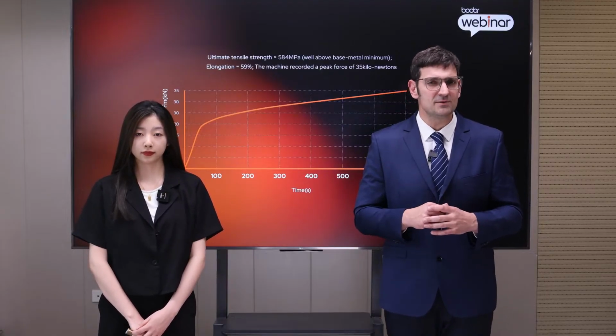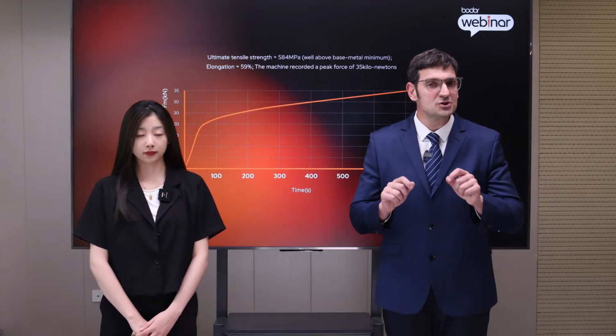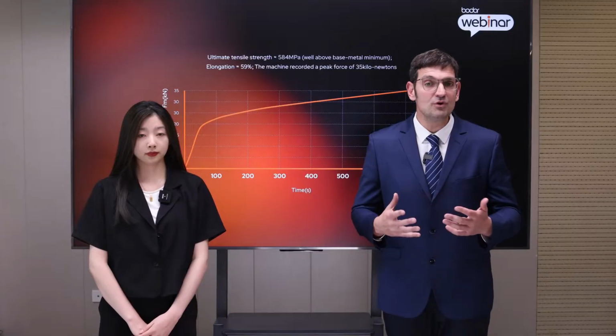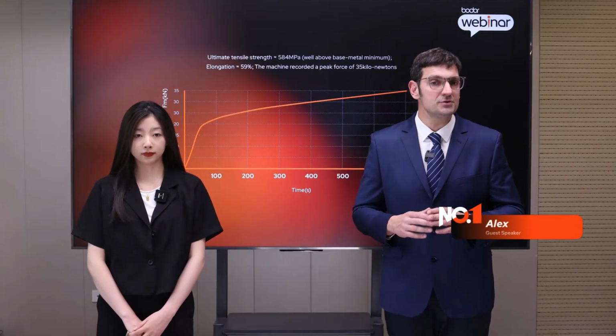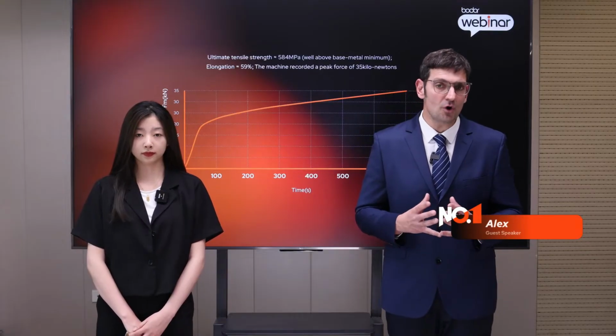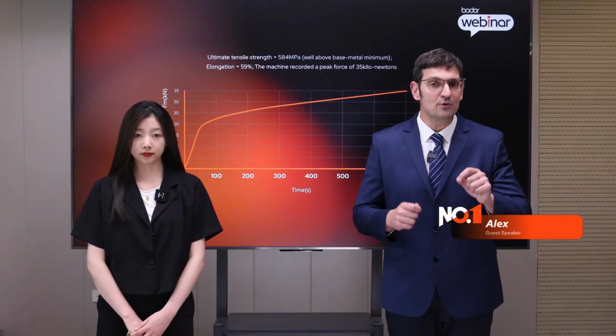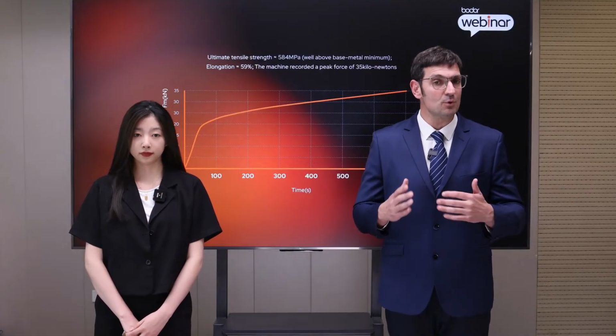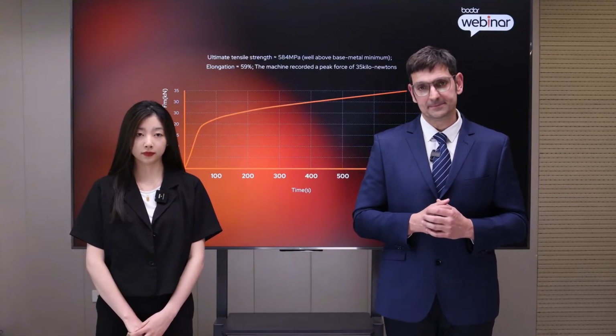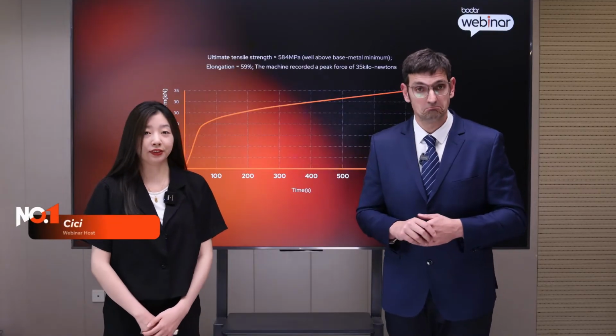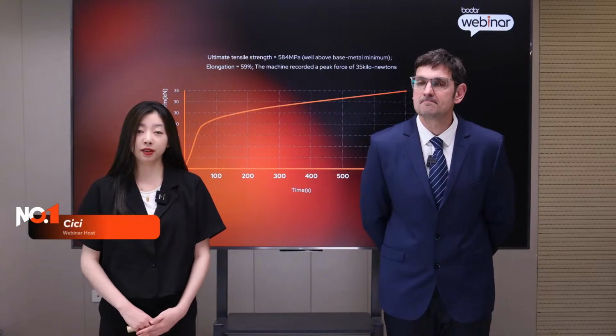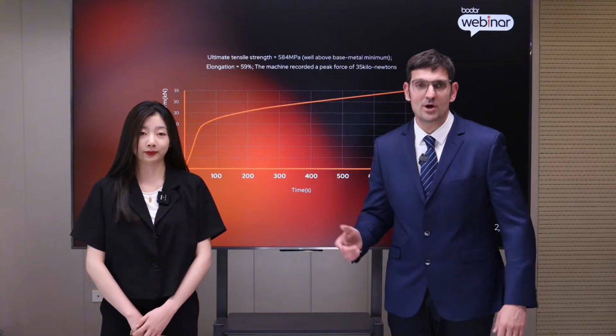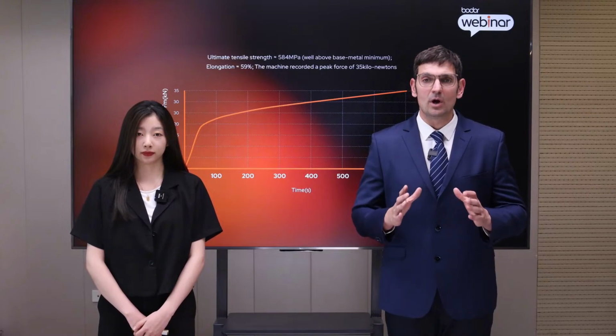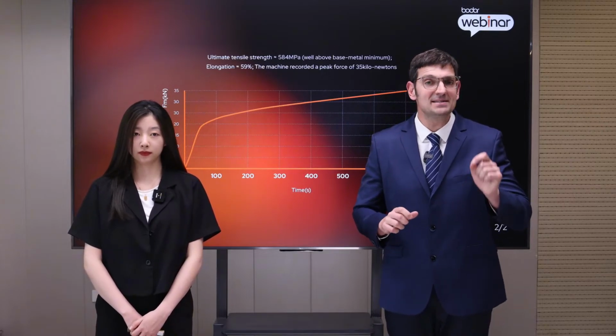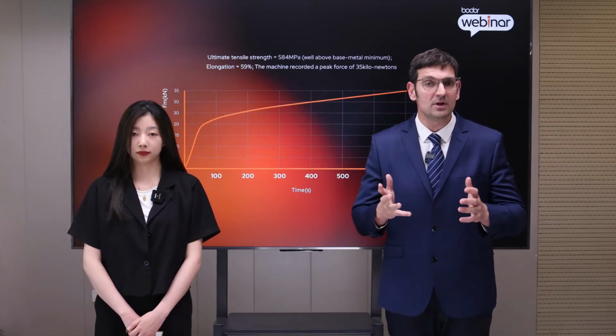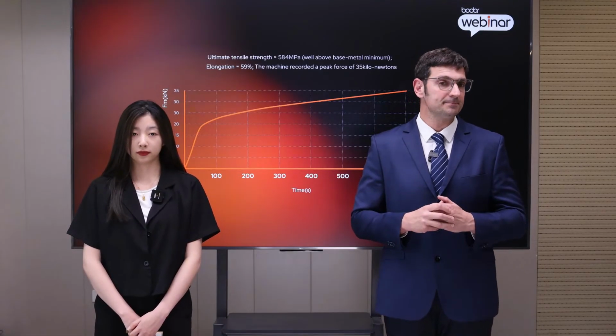And here's something really impressive. Before it broke, the welded strip stretched by 59% of its original gauge length. That level of stretch means the weld isn't just strong, it's not brittle. It can handle vibration, impact, and even forming after welding, without cracking or failing. That's impressive. But what does that really mean in terms of practical use? Great question. It means our handheld laser welds can actually pull harder than the base stainless. Yet, they're still flexible enough to bend nearly 60% before breaking.